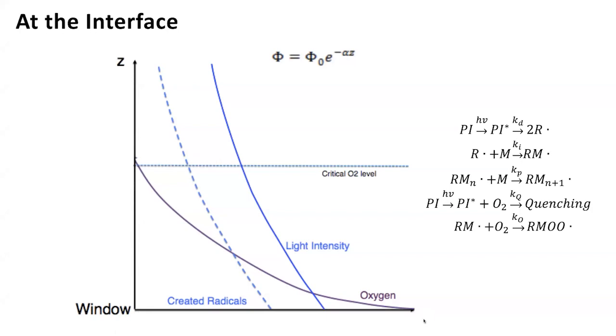And so what happens is, as light comes through the window and exits into the liquid reservoir above it, the intensity of the light is at its highest as it exits the window. Then its intensity will decrease with distance just through molar absorptivity, right? Or scattering. And that light is creating radicals. So the concentration of radicals in a free radical polymerization, because the resin's formulated with a photoinitiator, will basically track with the light intensity as a function of distance.